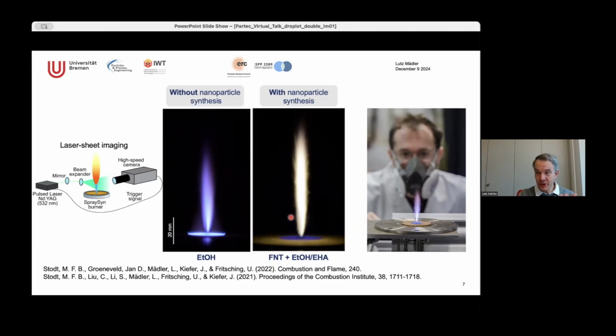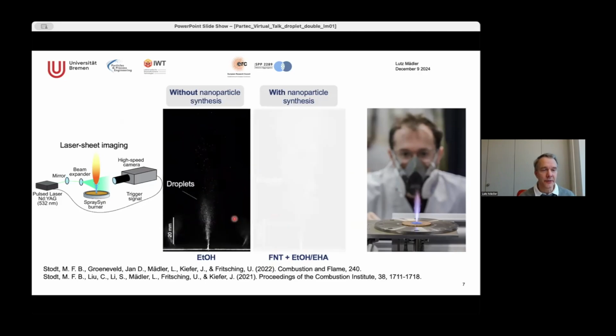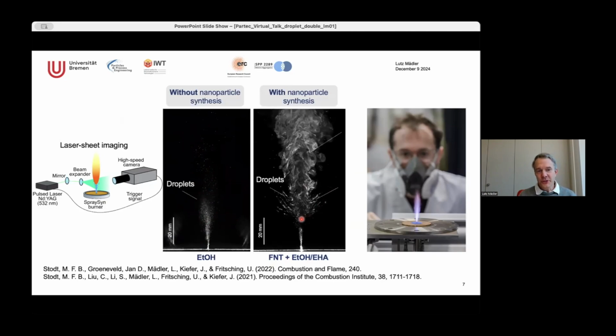But if you look with the flame sheet into these flames, you can actually see the droplets. Okay, there's a very thin sheet, and then in that thin sheet, you can see the droplets of that flame. And if you put the metal inside, things look completely different. Okay, so what you see here is some droplets that look like they are fireworking, and then you have this fume, kind of a mist fume, and these are actually the nanoparticles. The very small nanoparticles basically scatter the light here. And the question is, what is really different? You see a real difference, and the difference is you just put that metal.